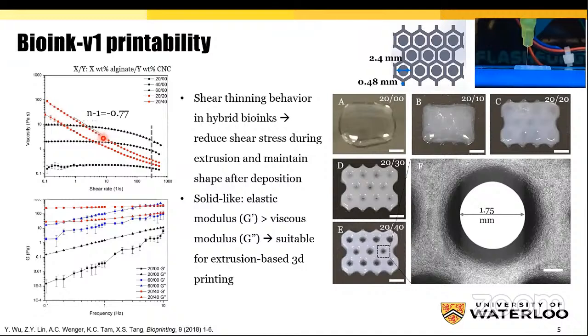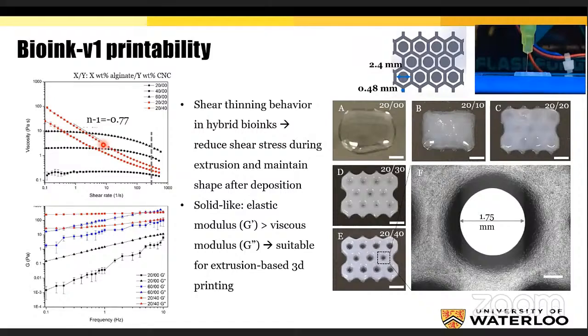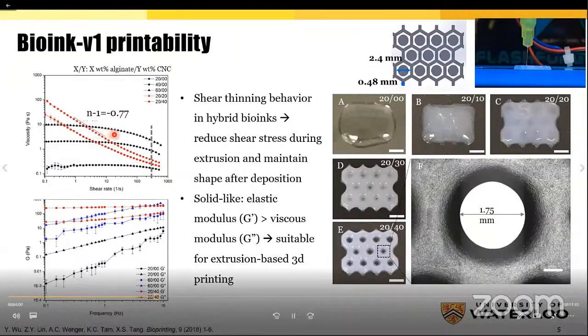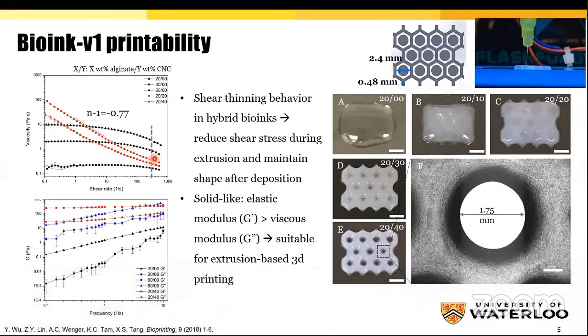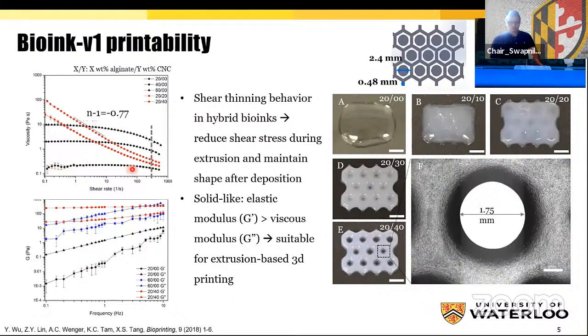In the shear thinning region, the flow curve conforms to the power law model. Taking 2040 as an example, the slope is negative 0.77. An estimated shear rate at the nozzle wall while printing can be obtained based on the flow rate, the nozzle radius, and the value n. We conclude the applied shear rate at the nozzle wall is around 300, and the viscosity is 0.5 pascal-seconds. This value is roughly 3 orders of magnitude lower than those at low shear rates, enabling the bioink to be extruded through a 100 micrometer inner diameter nozzle with no clogging.